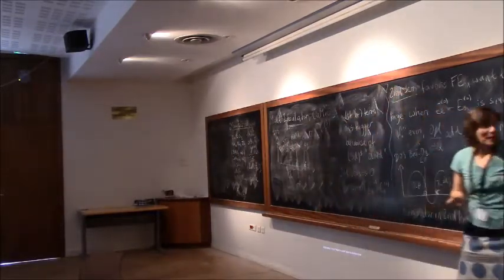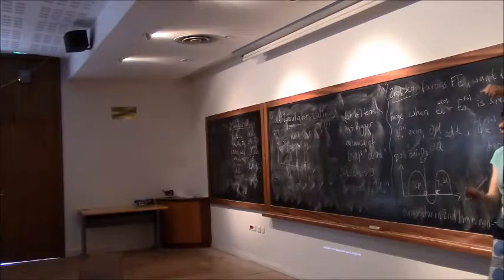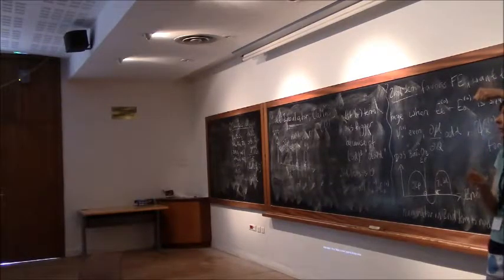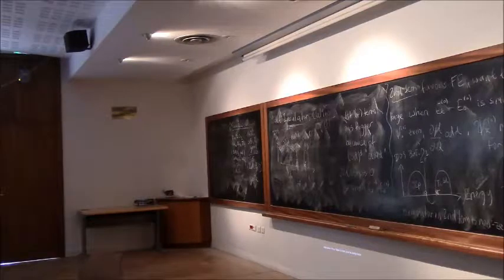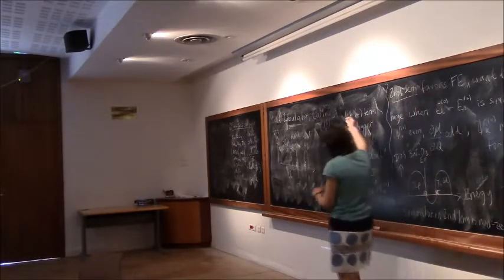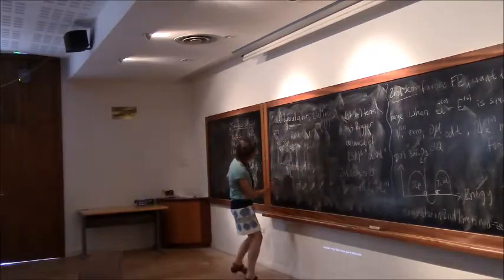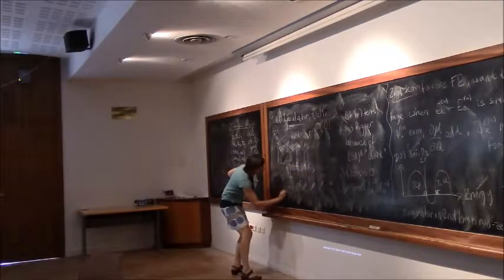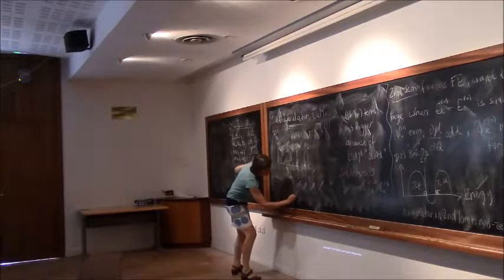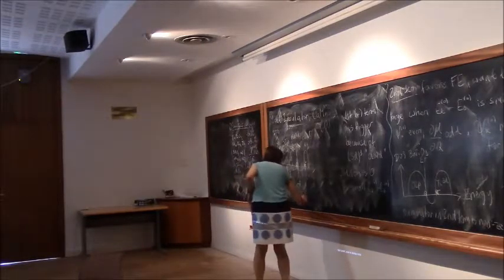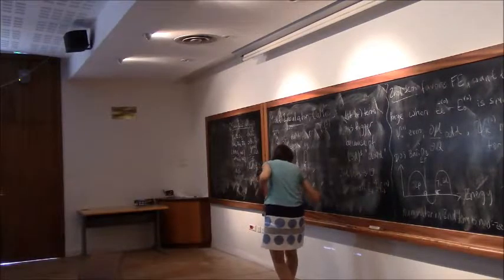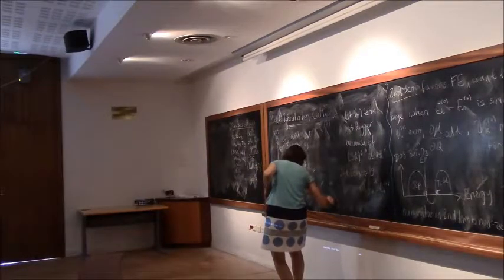Essentially, when I strain it, I elongate along one axis, and I make this term smaller, because I make the axis longer, and so I get less Coulomb repulsion when I push the ions towards each other. But the balance for just the regular material means that it tends to not be ferroelectric. But of course it is magnetic. It's an antiferromagnet. It's not a ferromagnet in this case, but it has local moments, so it's an antiferromagnet.